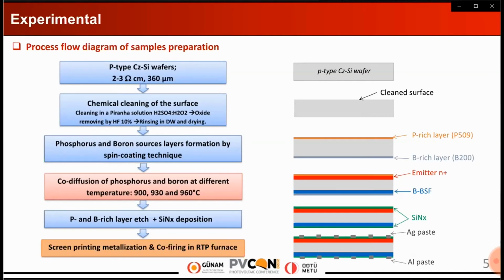Each deposition is followed by rapid drying in order to partially evaporate the organic species from the emulsion and solidify the layer. After the deposition of the source layers, the wafers are directly introduced into a quartz tube furnace for the co-diffusion of the dopants. The process starts by drying and baking to totally evaporate the organic species from the source layers. Subsequently, the wafers were subjected to annealing at elevated temperatures to ensure the co-diffusion of phosphorus and boron into the silicon matrix. This co-diffusion process was done in nitrogen ambient and at atmospheric pressure.